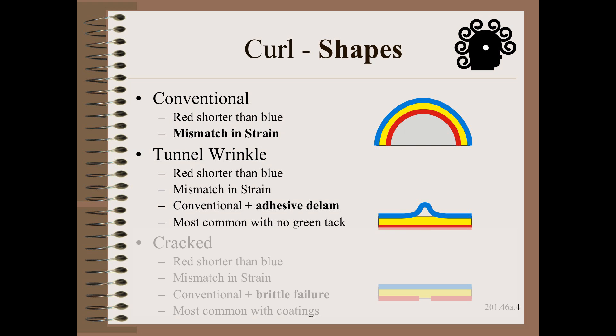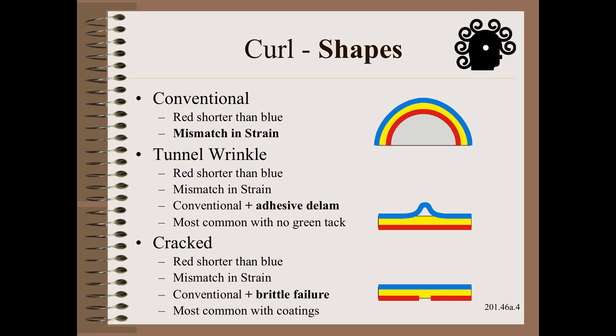Also, along these same lines, coating people do not often understand that cracked coatings are the same as curl with one tiny difference. That is, tensions in the coating cause the coating to crack instead of pull the web into curvature. In all of these cases, the blue wants to be longer or wider than the red bottom. The only difference is whether the adhesive or coating gives way in the process.